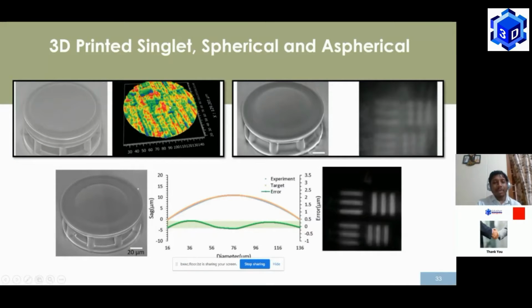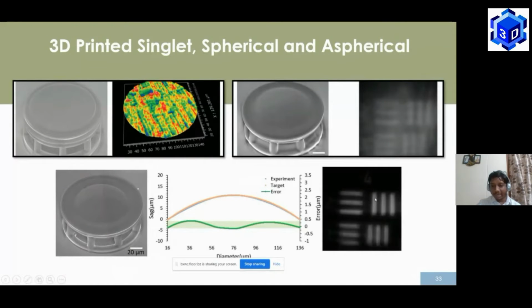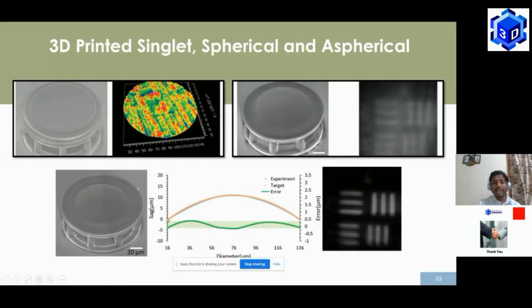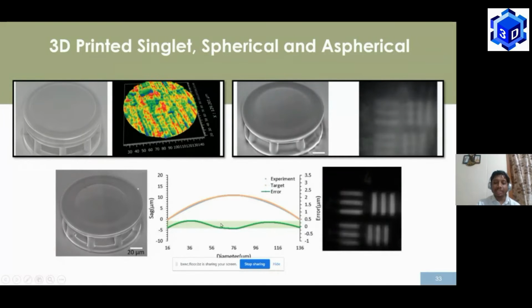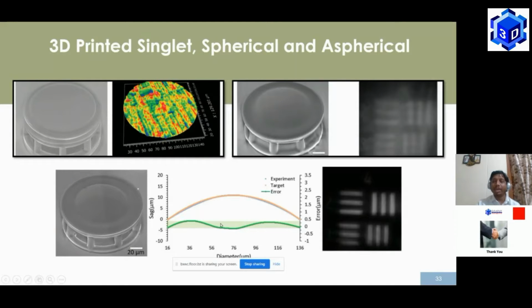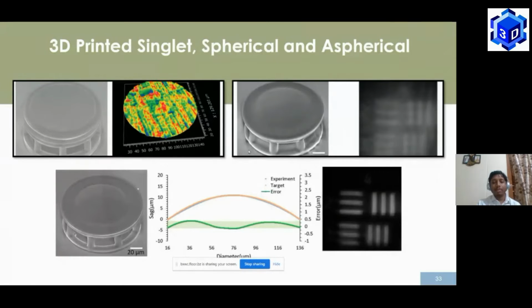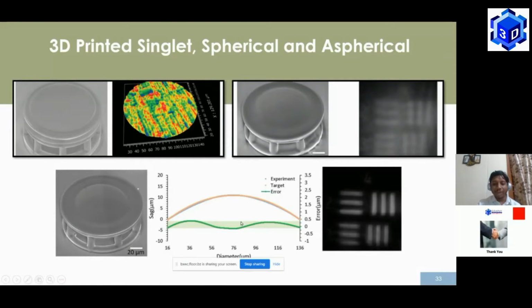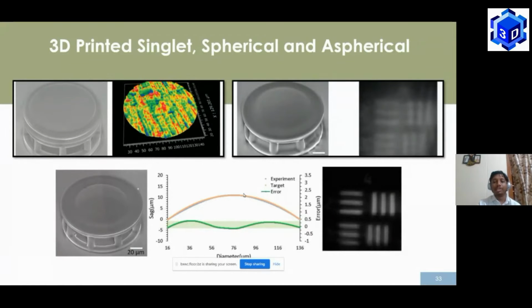This is the surface roughness image of a 3D printed lens, which is around 5 to 6 nanometers. The second image on your right is a spherical lens where the focus is not yet achieved. When we print with the aspherical lens that I showed in a couple of slides before, we were able to achieve better focus. And the center image is the designed shape of the lens. We are not yet 100% there, but this result is very encouraging for us to go for 3D printing in optical lens systems, because the error is almost less than a wave, and it really encourages going for the 3D printing of lenses in the future.